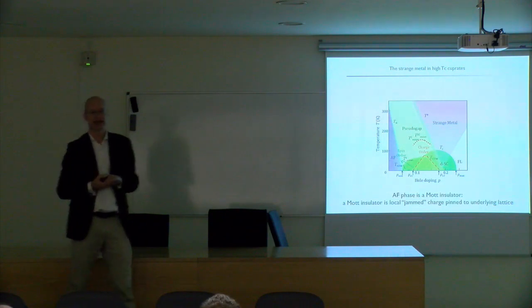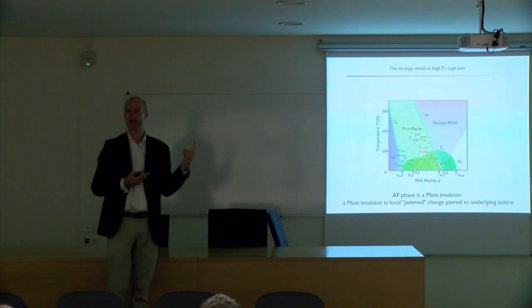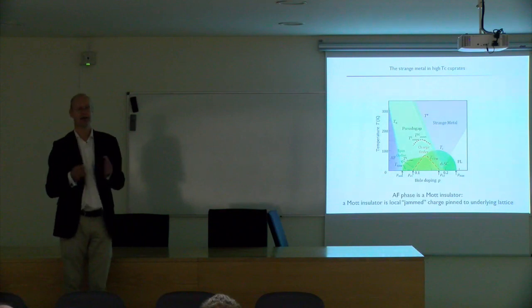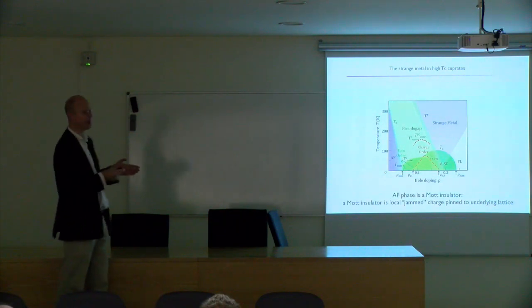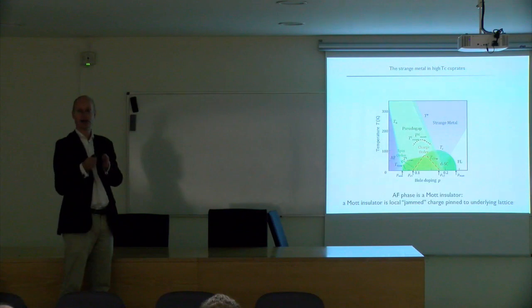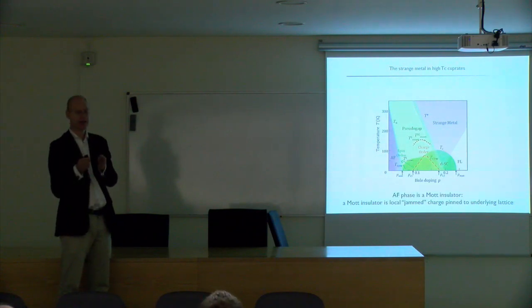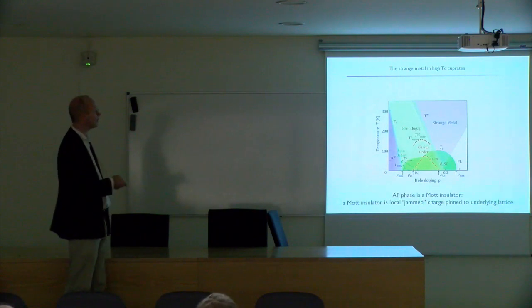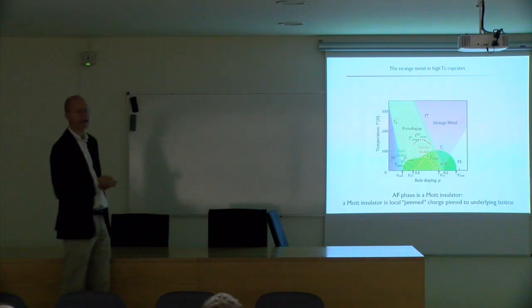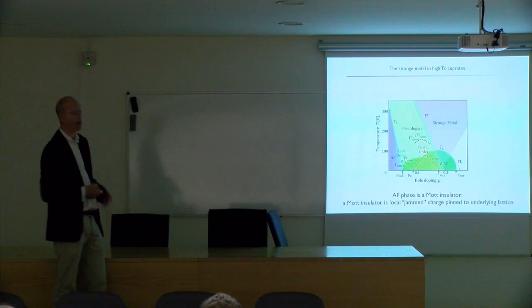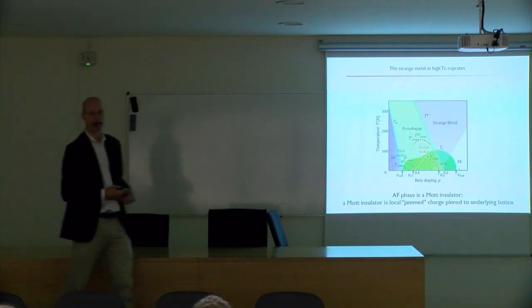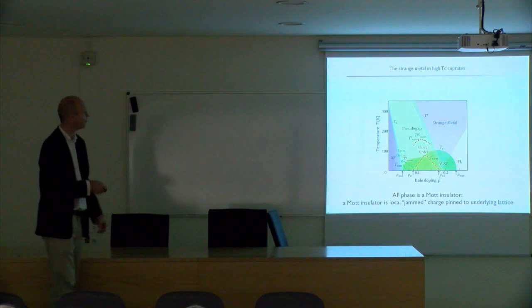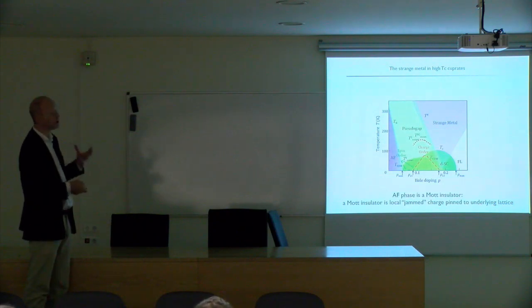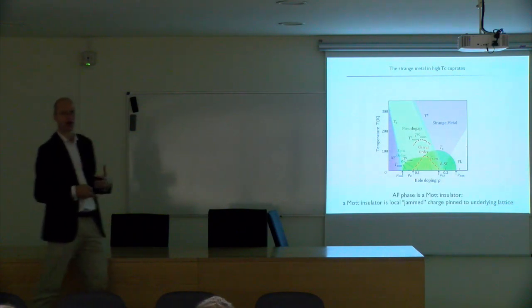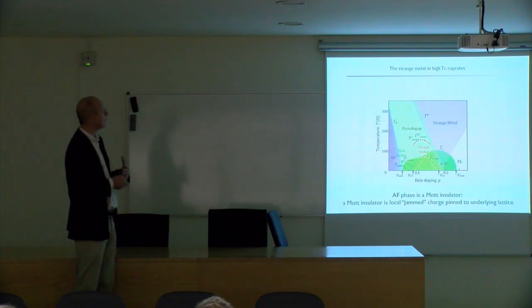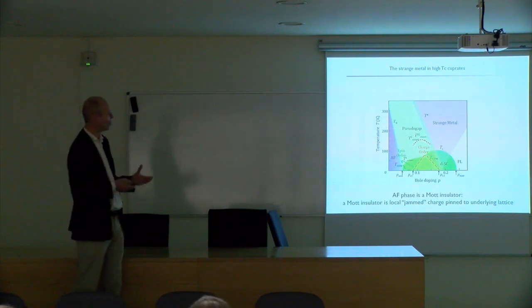What do I mean by that? If you have a very characteristic density of electrons, where the density of the electrons is precisely that you have one electron per atomic lattice cell, then something very funny happens: these electrons want to form a grid because they electrostatically repel each other, and this grid then locks into the underlying atomic lattice and doesn't want to move. There's a small energy barrier to move. That is called a Mott insulator. They're usually antiferromagnets because the spin alignment of the electrons wants to be opposite. So a Mott insulator is just locally jammed charge pinned to an underlying lattice.